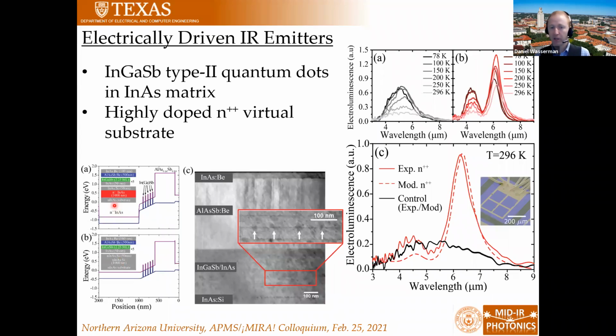That's essentially a quasi-plasmonic. This device is in fact not plasmonic. The permittivity is not negative at the wavelength of emission, but regardless, you still get this cavity effect. And if you compare the undoped emission to, and this is electrically driven, the doped emission, you see again this sort of dramatic enhancement. So not only can we do this with just a thin layer on one of our plasmonic surfaces, but we can integrate this into a PN junction device because, of course, our plasmonic material is nothing more than an N-doped semiconductor. So it's just the N++ part of a PN junction device.